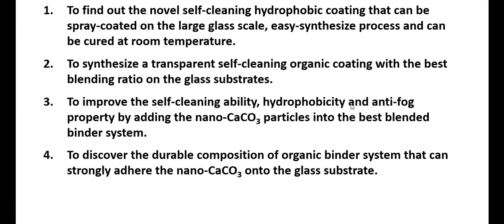Okay. Next. So our main objective is to find a novel self-cleaning hydrophobic coating that can be spray coated on a large glass scale, with an easy synthesis process, and can be cured at room temperature. We don't want any oven curing process over here. So there is no oven curing process. It can be cured at room temperature at ambient condition. Okay, number one. Number two, to synthesize a transparent self-cleaning organic coating with the best blending ratio on the glass substrate, and to improve the self-cleaning ability, hydrophobicity and anti-fog property by adding nano calcium carbonate particles into the best blended binder system.